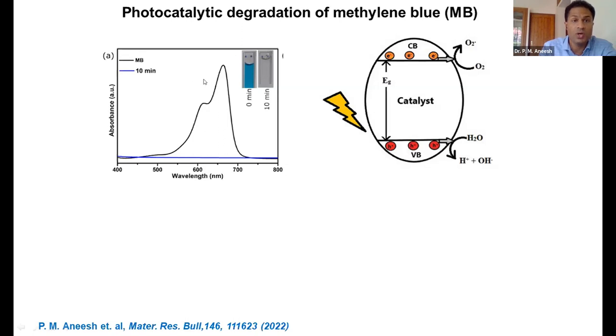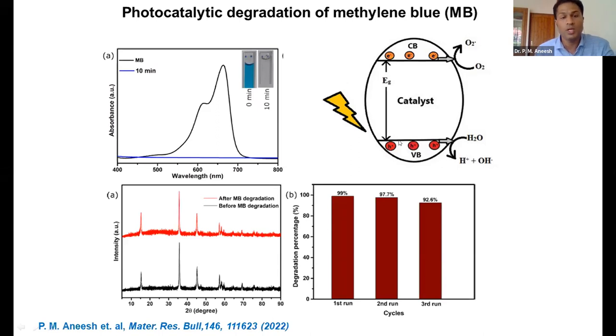And this is the result we got when it is treated with 5 milligrams of VS2. This is the methylene blue photoluminescence absorbance. When it is treated with 5 mg of VS2, you can see the peak is reduced, which means methylene blue is degraded into some harmless product. So this is the mechanism that I mentioned, and in the inset you can see the color of the sample initially, and after the treatment with 5 mg of VS2, the color turned to pure water.